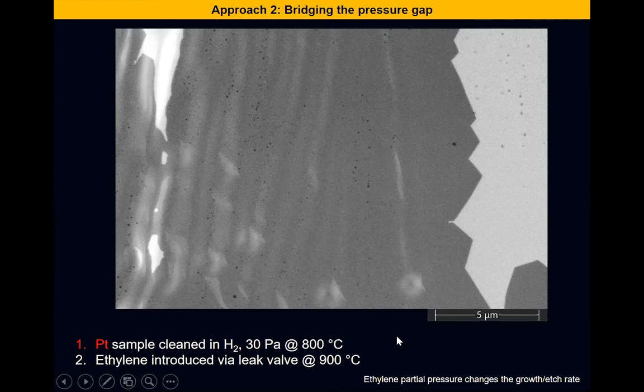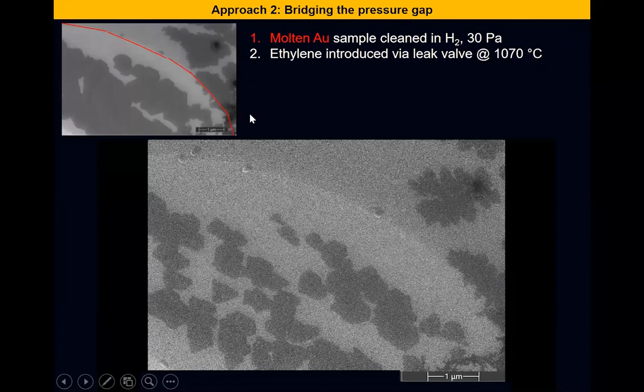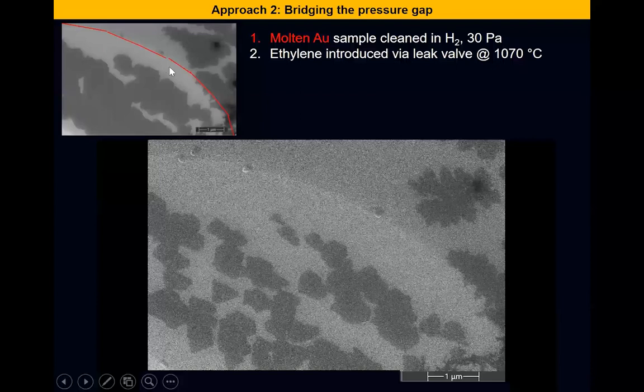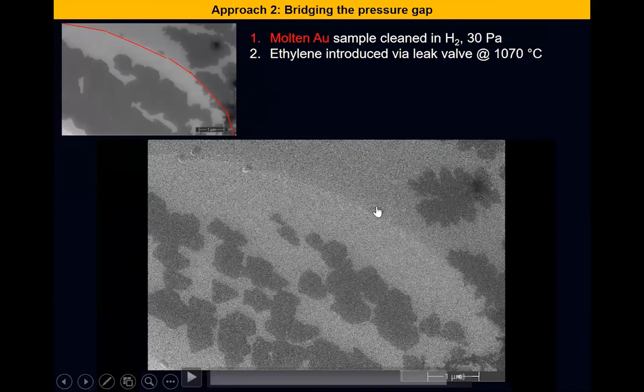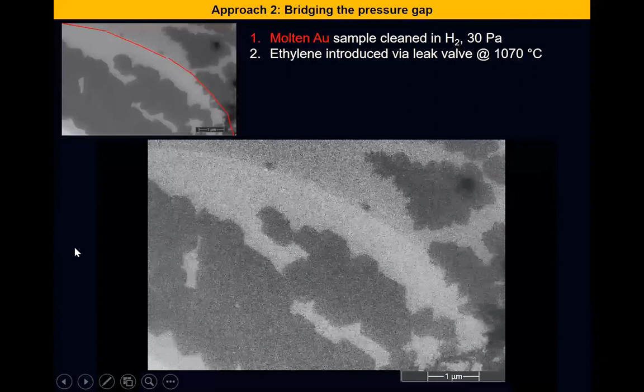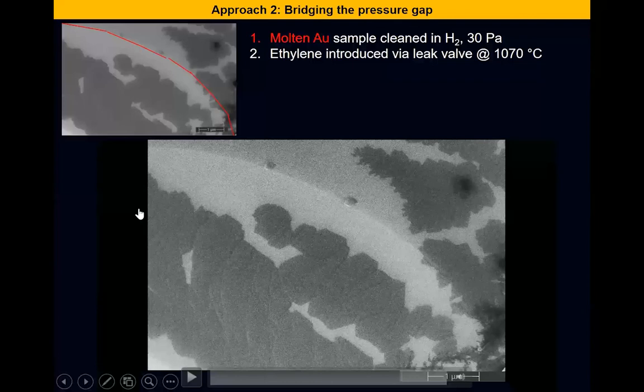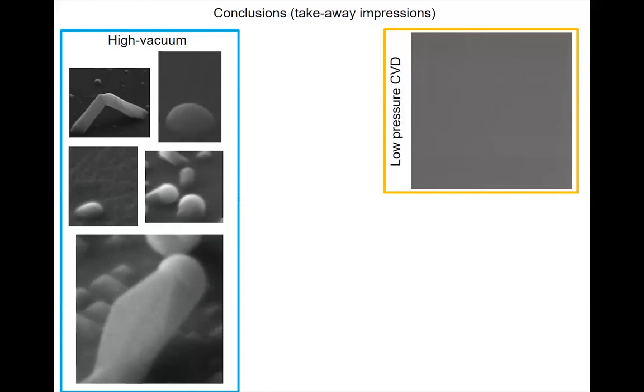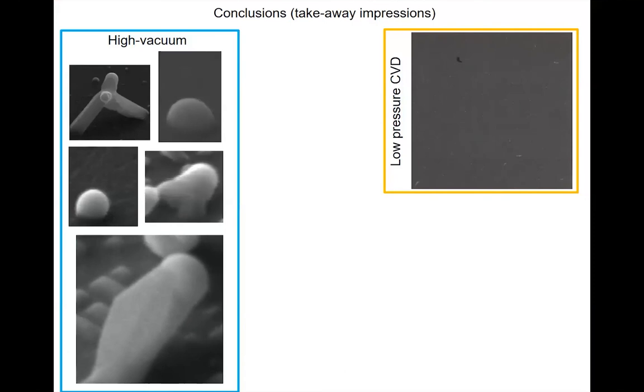The last example is graphene growth on molten gold, which we attempted just a few weeks ago. You can see two domains on the semi-liquid gold: one shows hexagonal growth of graphene, which is limited by attachment kinetics, and the other shows fractal growth, which is limited by diffusion. We can observe the growth of graphene in two different modes on a single sample under the very same conditions. Studies like this are very helpful for growth optimization of monolayer two-dimensional materials. We have shown just graphene, but we are heading towards more advanced materials like transition metal dichalcogenides.